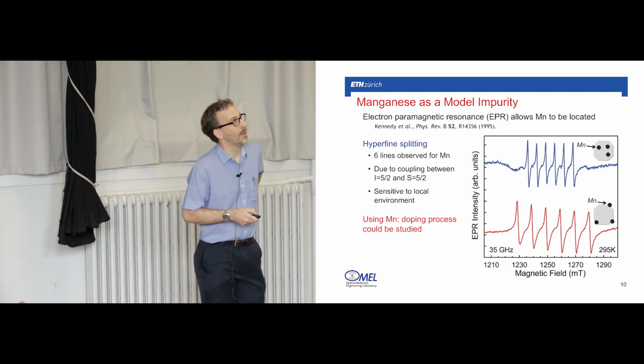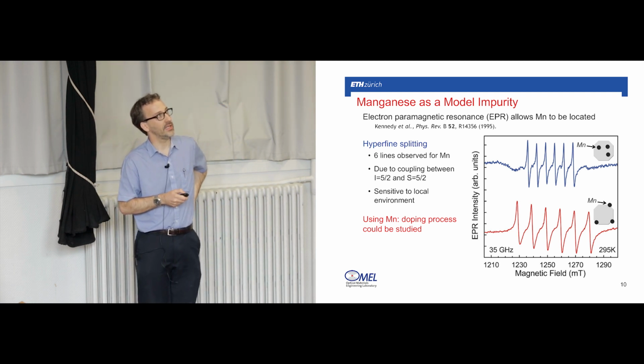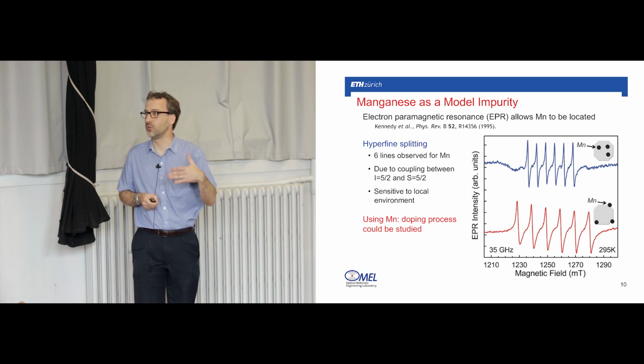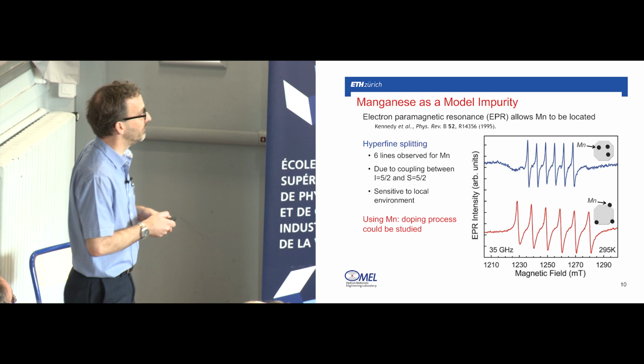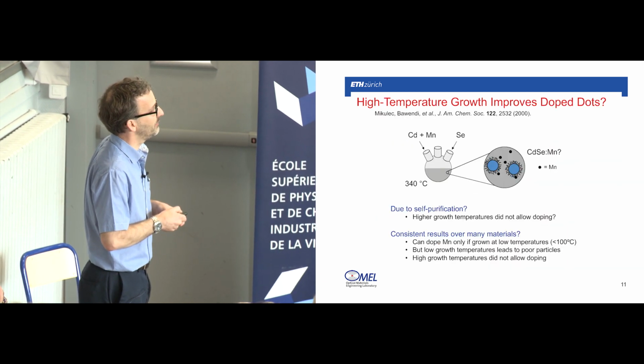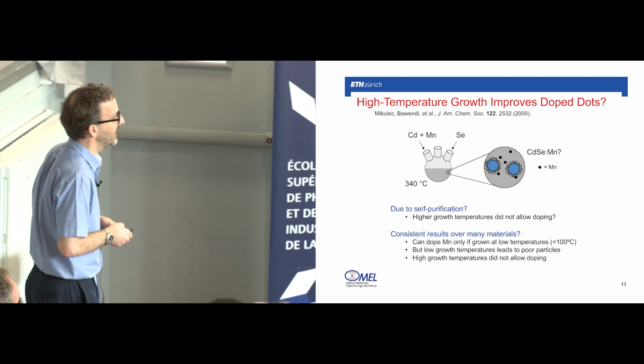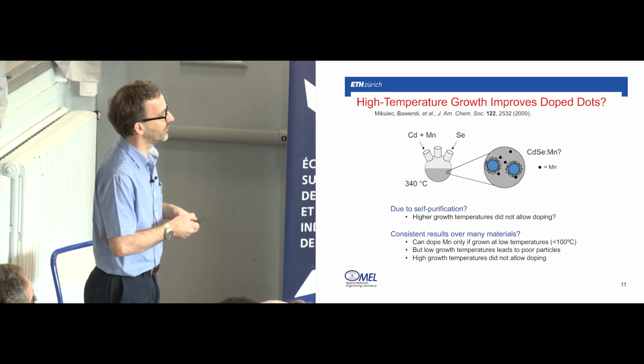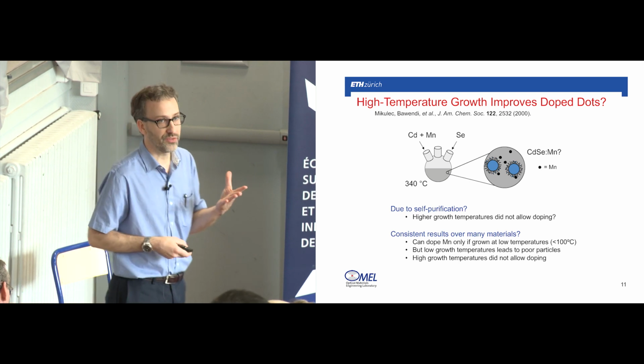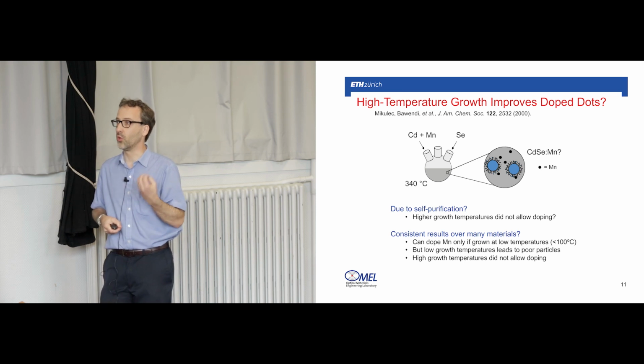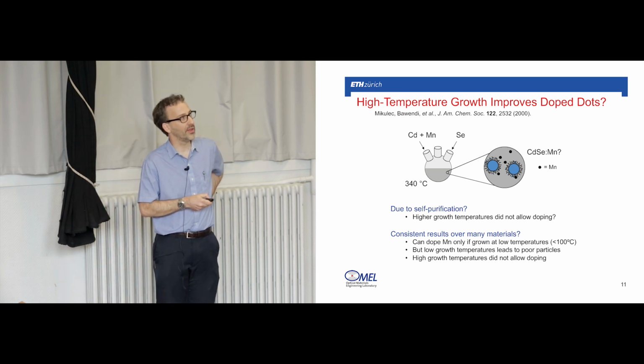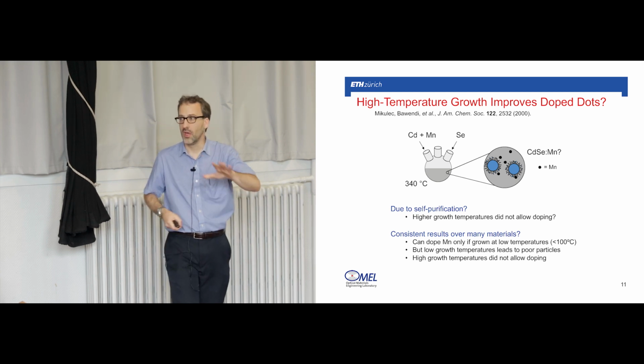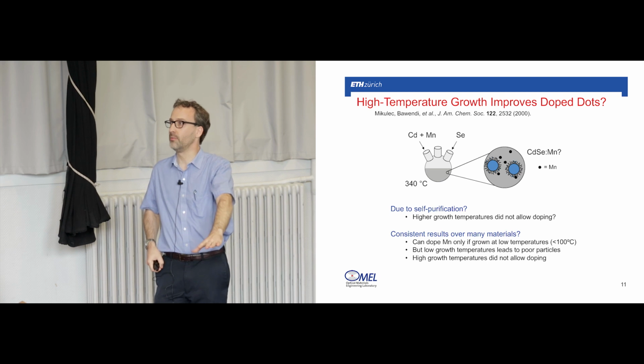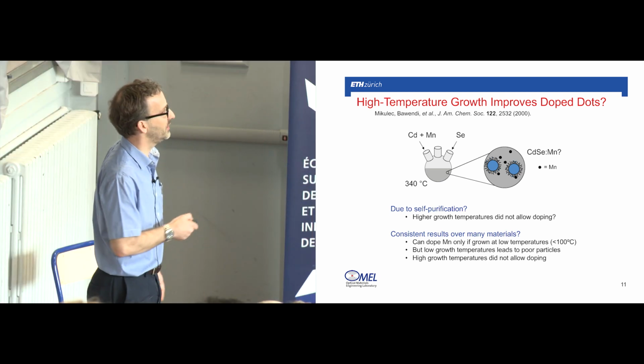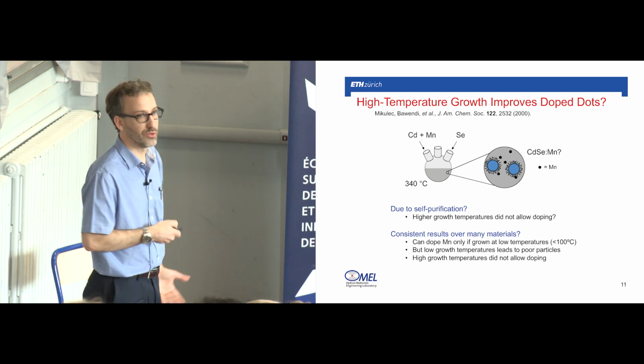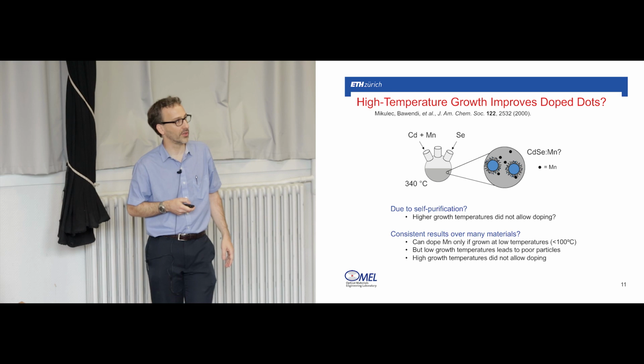What the Bawendi group did in the 90s was do what I just posed: take these newer synthetic methods and try to improve the doping of dots. They took the cadmium selenide prep and added some manganese precursor, and then did a lot of very careful characterization to figure out where the manganese was. They always found that the manganese was excluded from the particle, or was not incorporated, let's put it that way. And so again, the question arose, was this due to self-purification? Because the Bhargava work was done at room temperature, diffusion might not be so active. This is grown at higher temperature, maybe diffusion starts to be active, and so this might be the reason why doping doesn't work: self-purification.